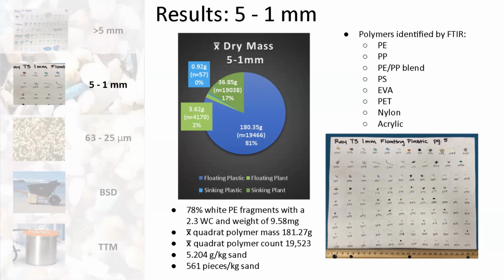This is how much was in each quadrant, close to 20,000 particles. Our average weight is 5.204 grams per kilogram of sand. That's greater, again, than what our meso and macroplastics were. With each kilogram, or almost a handful or 2 handfuls of sand, you're getting about 561 pieces in there. So we have 2 additional polymers that were found in this size category compared to the other. And again, some plastics that sunk in that process, a very small amount, and some natural material that didn't sink in that process.